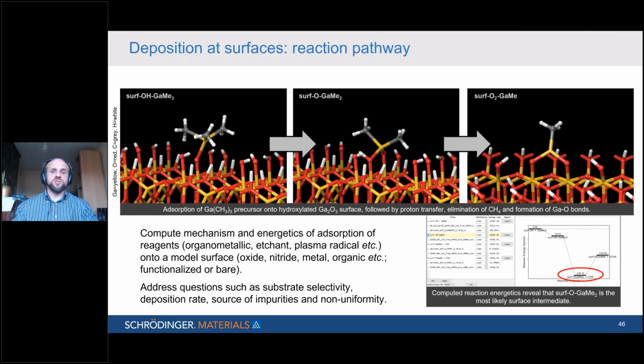So here are some examples of what we can do. The key thing is that density functional theory is at the base of this, but we build on it workflows that are useful for this and other technology areas. So we have workflows for generating surfaces, for putting molecules on surfaces, for analyzing the energies that come back from density functional theory, and for putting them together into reaction sequences. This is the typical ALD reaction sequence. So atomic layer deposition is a way of growing films in a very controlled fashion, layer by layer. And here we see trimethyl gallium, which is a precursor for gallium, reacting with a hydroxylated gallium oxide surface, as would happen in atomic layer deposition.